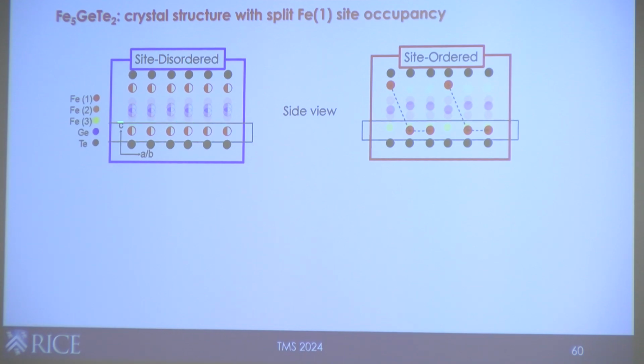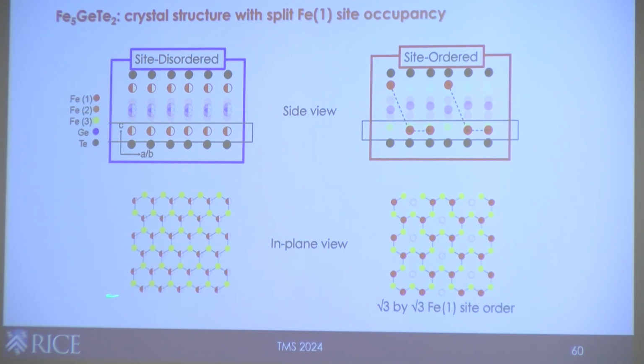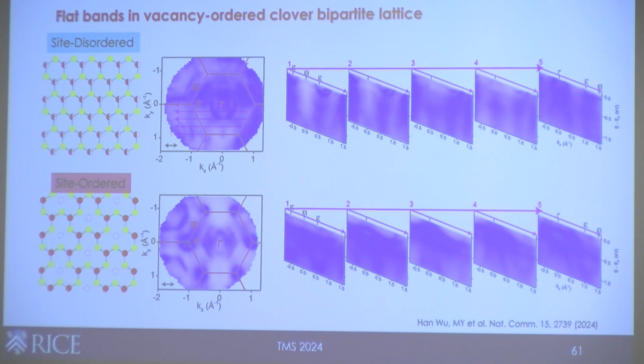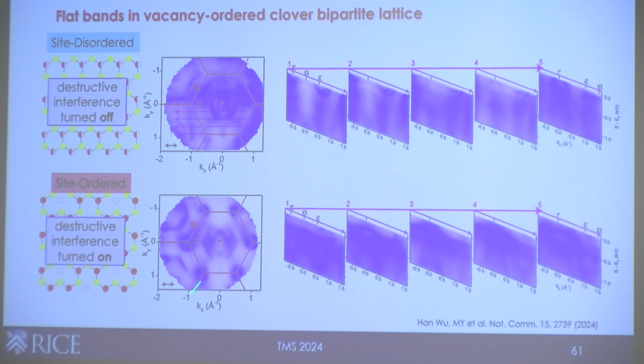The reason is that if you actually look at the horizontal slice, which is affected most by this vacancy order, it is this slice, and this is where the shortest bond actually occurs within the unit cell. And immediately, you can see that this is the view I showed you earlier. In the in-plane direction, this is the system that's this honeycomb lattice, and this is the one that has this clover lattice. So if we do ARPES on this, you can see they have drastically different electronic structures, and the most important thing is that for the bottom one, where you have the site order, bipartite lattice, you actually end up with these flat bands. You can see them pervade over a large portion of the Brillouin zone. And this one, you don't have those anymore. And we can understand this now because you have destructive interference in this vacancy order phase, but not in the upper one, right?